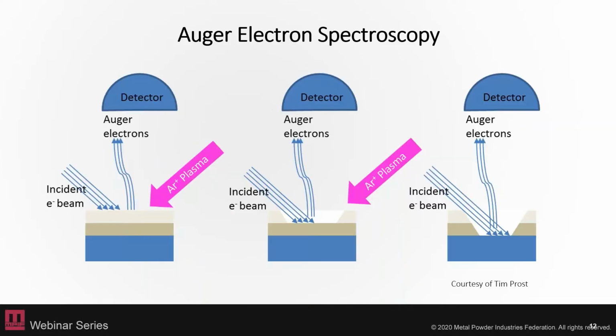Another measurement that we found really helpful in-house for characterizing our powders is Auger electron spectroscopy. This one isn't very common across the industry, but I really hope that it becomes more so. This is where you have an electron beam measurement, where the electron beam is going onto the surface of the material, and then the detector is picking up the Auger electrons that are coming off of those atoms, and then you can use an argon plasma to etch away the surface so you can get a depth profile of the material itself.